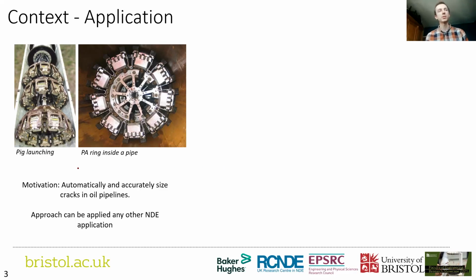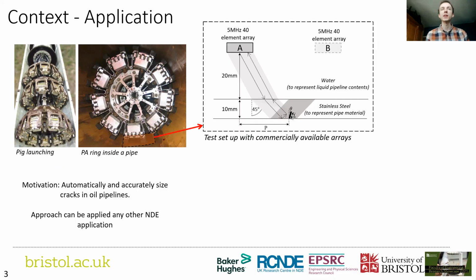So inline pipe inspection uses PIGs, or pipeline inspection gauges, that flow through pipelines in the flow of the product. So this would normally be full of oil, and you've got ultrasonic phased arrays in a ring here on the back, and they're used to inspect the pipe for things like corrosion and cracks. They fire ultrasonic plane waves into the structure of the pipe, and then you listen for responses from those corrosions and cracks. And if the online processing detects something, the data is stored, and then later it's looked at by a human to try and decide if that crack or corrosion is significant.